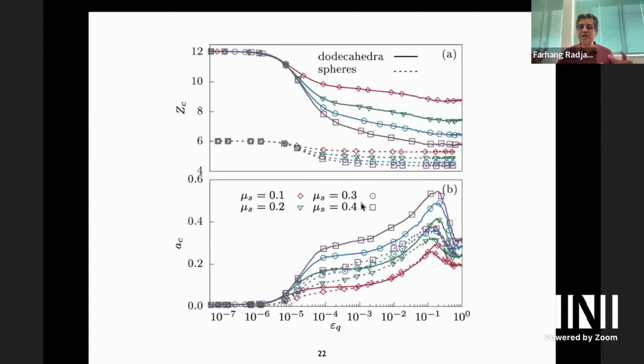So the connectivity of the particle network is decreasing, while at the same time the anisotropy is increasing. Here the anisotropy is 0 at the beginning because of the isostatic state. Then when the plastic deformation rearrangements begin, it increases and goes past through a peak.